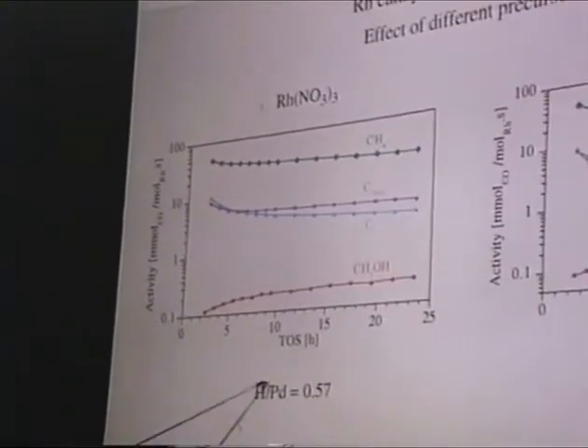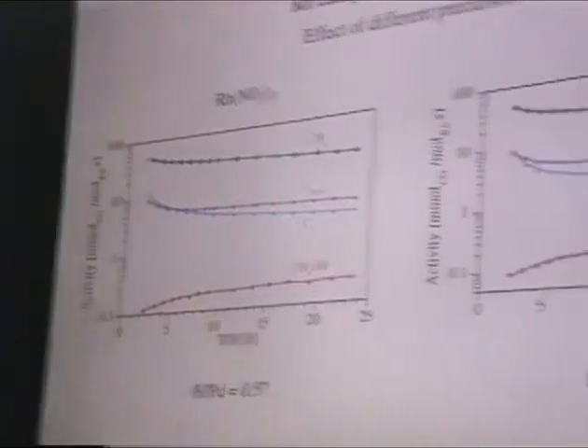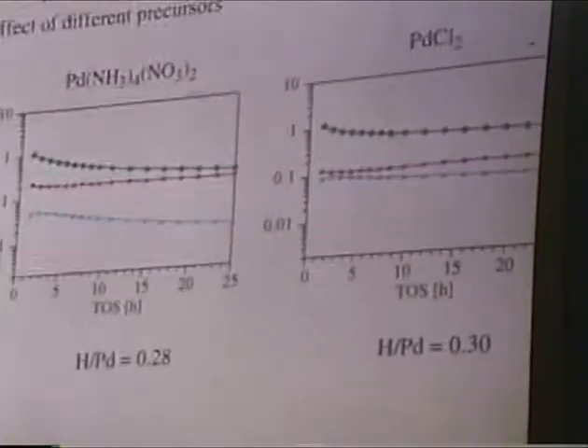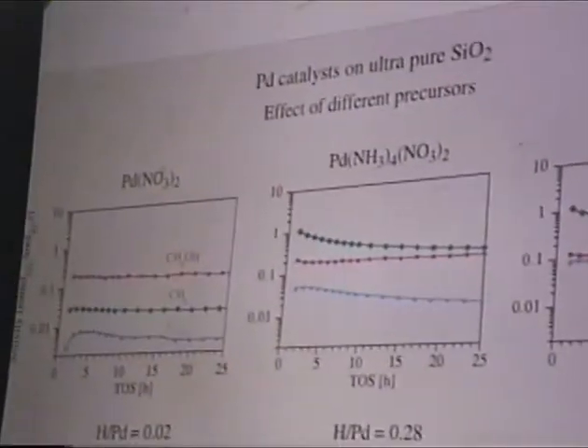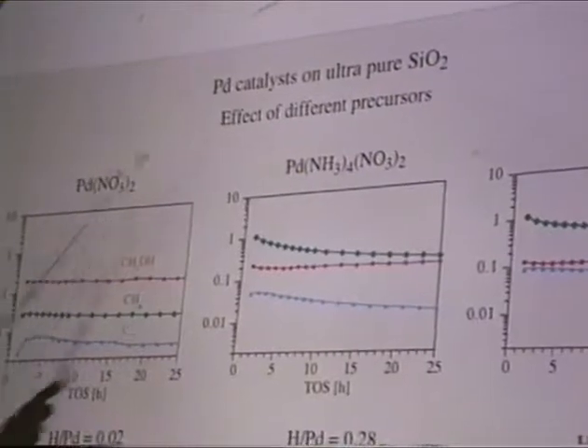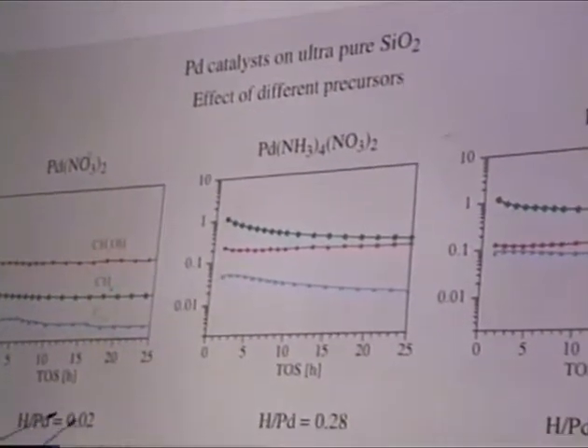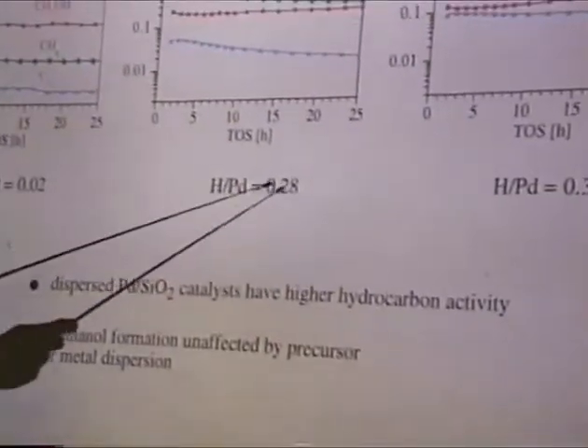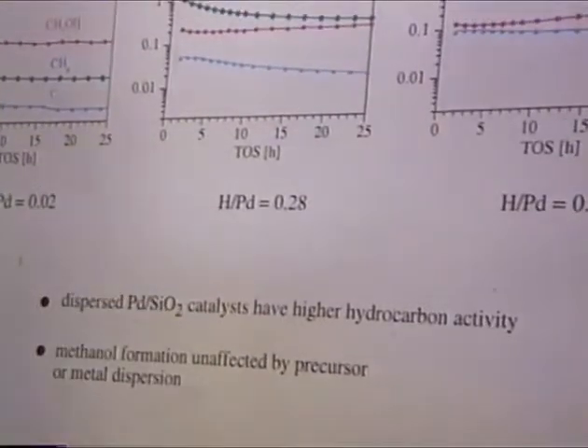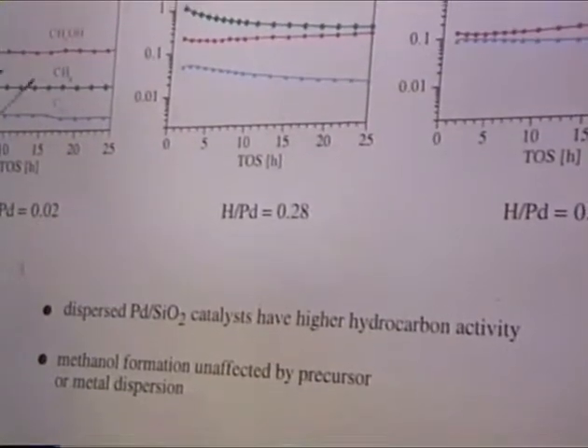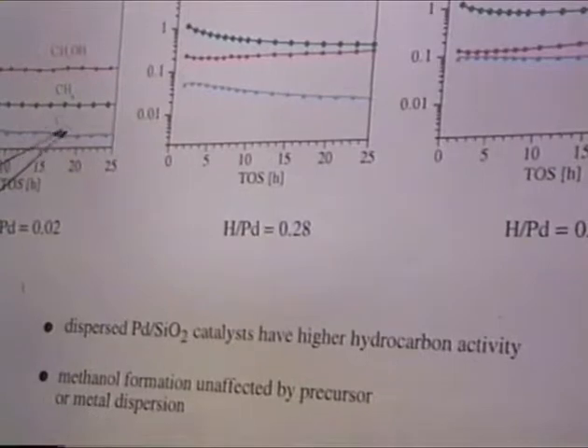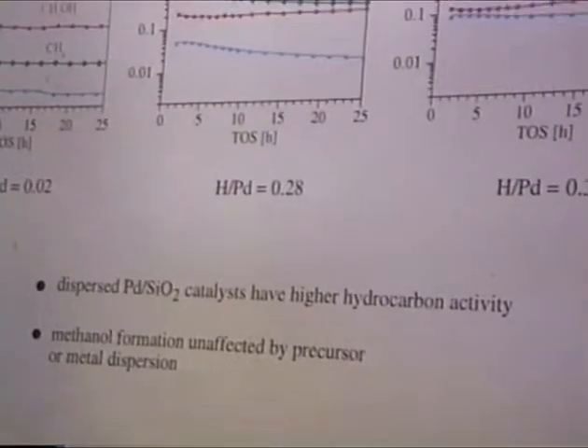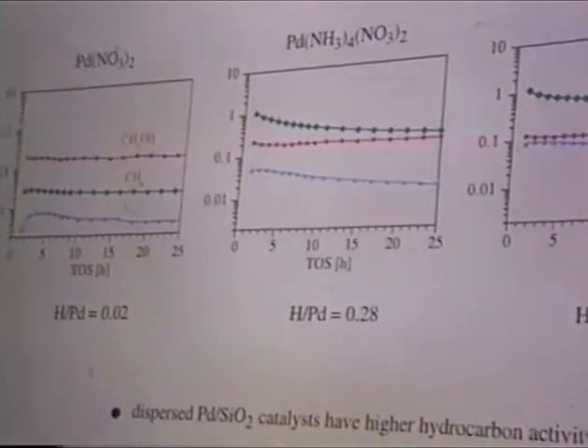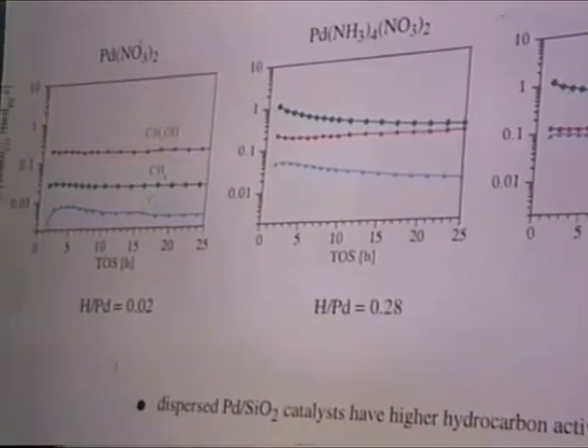So this is hydrogen over rhodium. The dispersion was the same here, just to cancel that effect out. The same for palladium. Although we had 3 salts and there's a different dispersion, very low, reasonably good, and almost equal to that, there is a difference in the methane and the C2+, and that depends on the dispersion. And the reason is, of course, that we know that palladium is very bad in dissociating CO.